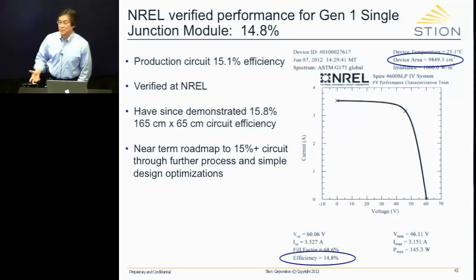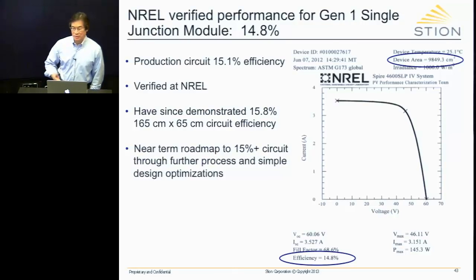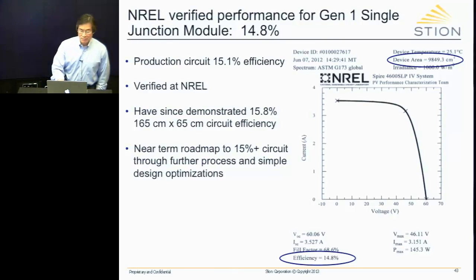We are not at full capacity because of the obvious reason of the marketplace right now. Nevertheless, our champion module efficiency as measured by NREL is 14.8%. The corresponding circuit efficiency is 15.1%. This is a full-size CIGS module, 1 square meter, 65 by 165 centimeters squared. Since then, we've demonstrated a circuit efficiency of 15.8% at full size, and we're getting ready to submit that to NREL as well. And we've developed a near-term roadmap to get to 15+% efficiency at the module level. Our target is to get to 16.